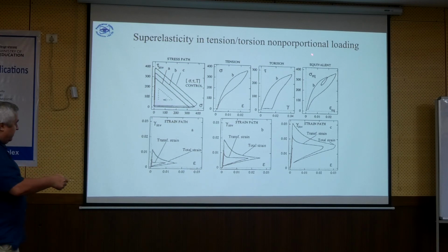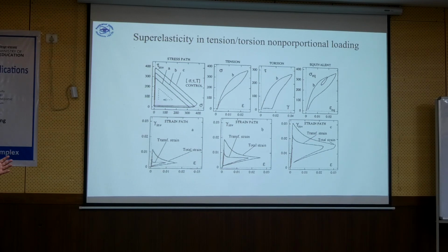And this actually, when we look on the sample, we could see it. Some of the plates get back, yeah. And this is the major difference between the copper-based alloys and nitinol, and basically between the nitinol and most of the alloys.